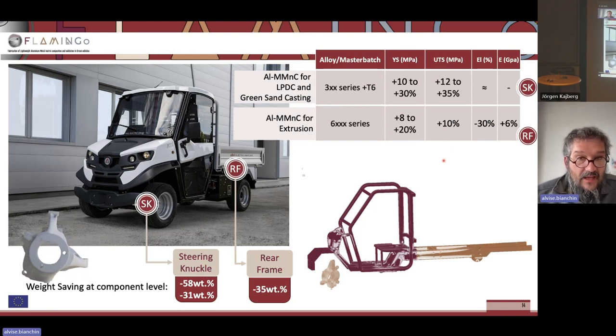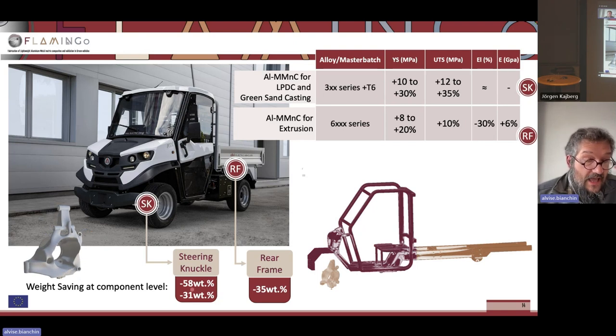So just a quick slide about some of the interesting results that we had in terms of increase of yield strength and ultimate tensile strength for different conditions. We have now realized this steering knuckle, which can have different weight savings due to the different topology optimized geometries. The other component that we are realizing is the rear frame, which is obtained by extrusion, and also this one is heading to have a weight decrease of 35% compared to the current component for this vehicle, which is made in steel.